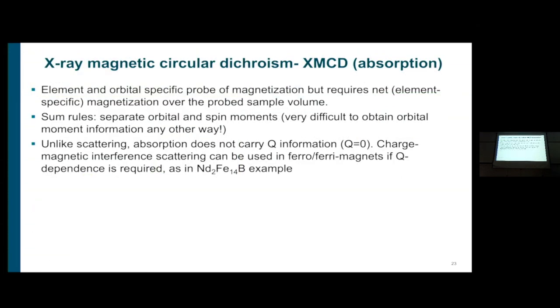So just to summarize the XMCD, again, it is element and orbital specific, but one limitation is that it requires net magnetization over the probe sample volume, because you need these bands to be spin polarized. So it's very different than the resonant magnetic scattering. You can probe antiferromagnets when you have no net magnetization, and you pick the magnetic Bragg peaks. Here you need net magnetization. You can separate spin and orbital moment, which is very difficult to do otherwise. There is no Q information, so we can never do the neodymium site-specific thing with this technique, because it will measure the contribution from neodymium, but it cannot separate sites based on symmetry, because there is no Q information. It's a Q equals 0